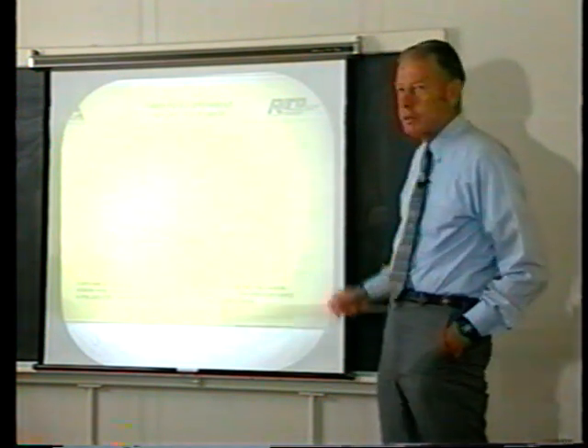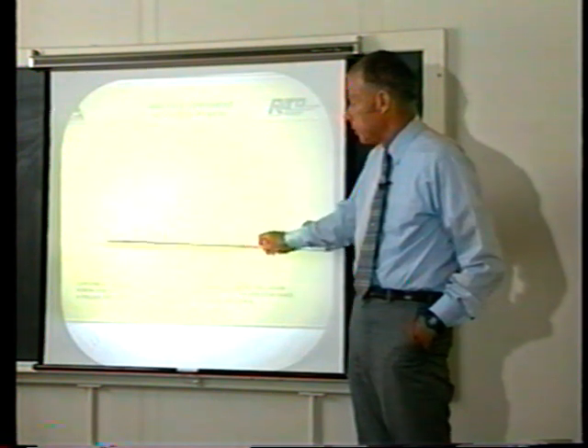An experiment ran in parallel with the one I just showed is this experiment. It had exactly the same conditions, but there was never any real strong evidence of excess power. You see fluctuations here, but it averages out pretty close to zero. So no significant excess power in this experiment, even though it was run in parallel at the same time under exactly the same conditions. We later found a reason for this.